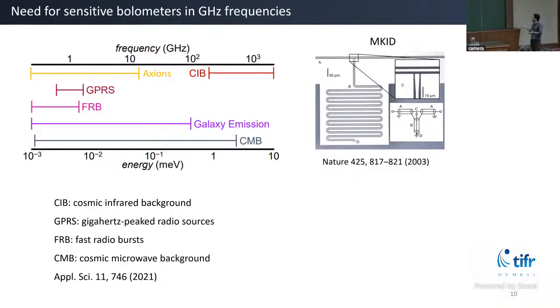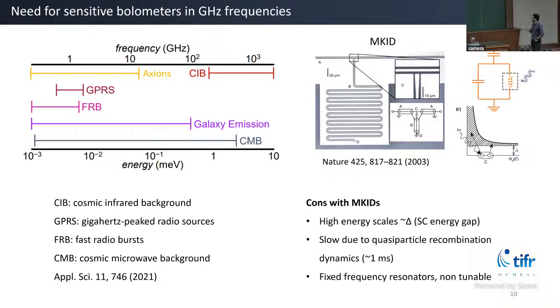One of the very common types is superconducting thin film-based kinetic inductance detectors. What they make is some kind of resonator arrays, and when, for example, a photon falls on it, it hits the superconductor and the Cooper pair breaks. So you get a resonance frequency shift in these devices. But since they rely on this Cooper pair breaking, they essentially work at a higher energy scale, which is the superconducting energy gap of your material.